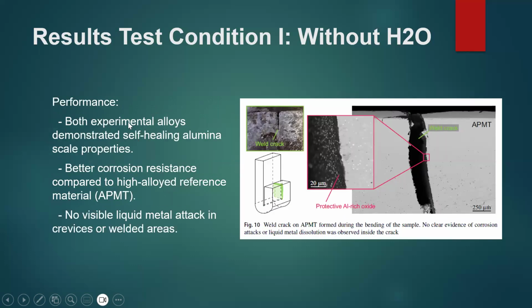Regarding performance, both experimental alloys demonstrated self-healing alumina scale properties with good corrosion resistance compared to the high alloy reference material APMT, and no visible liquid metal attack in crevice or welded areas.